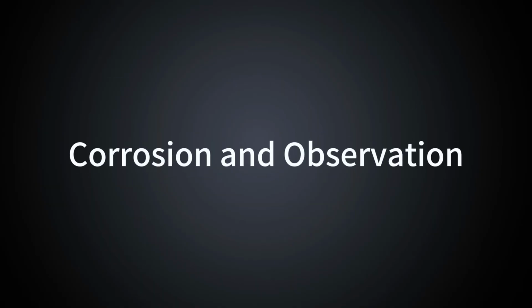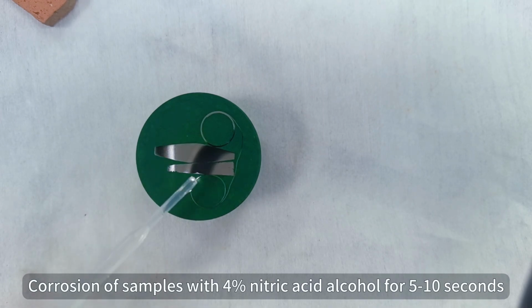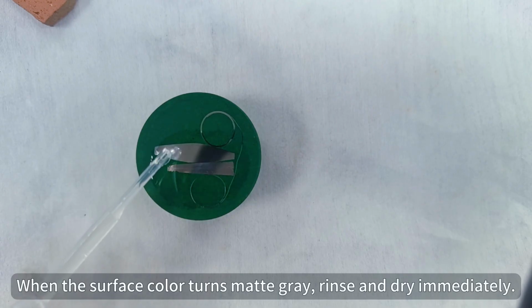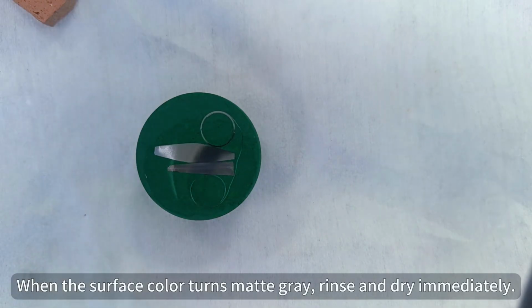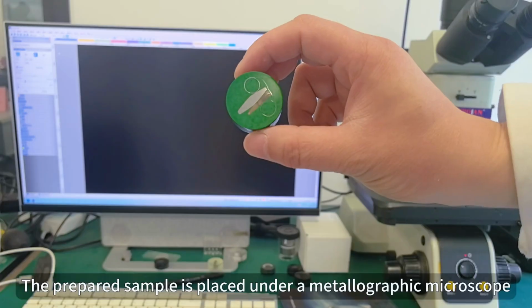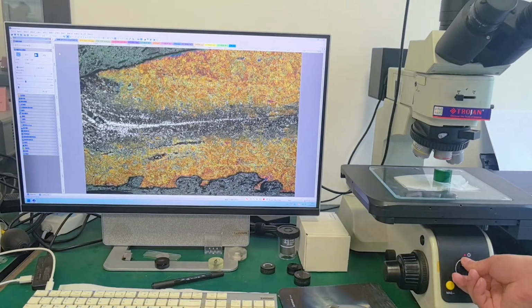Corrosion and observation. Corrode the sample with 4% nitric acid alcohol for 5 to 10 seconds. When the surface color turns matte gray, rinse and dry immediately. The prepared sample is placed under a metallographic microscope.